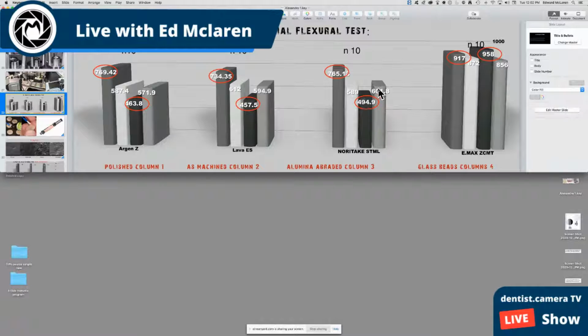So again, I'll revert back to this, sorry to be redundant, is if I want to bond it, which I do, the 5Y materials, I sandblast, but then I use a resin liner, obviously a resin cement, with an MDP primer, and the strength went back up. This was with a 60 micron layer of resin plus the 1.2 millimeter disc. But if I don't want to worry about any of that, people say, well, Jesus, Ed, I wanted to use this stuff because I wanted to use it like metal ceramic. I didn't want to go through all that stuff. I just want to use zinc phosphate, which you could use, I guess. Glass ionomer would be the recommendation, or resin reinforced glass ionomer. Then I would go with the 4Y material because it looks pretty good. So that would be my general recommendation.